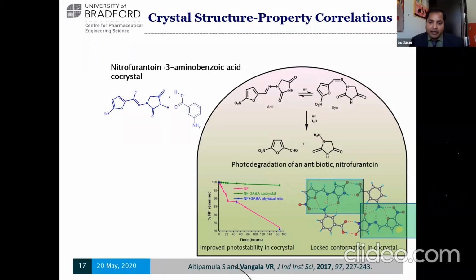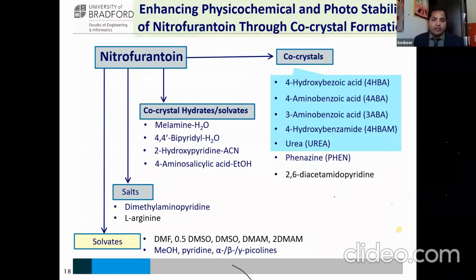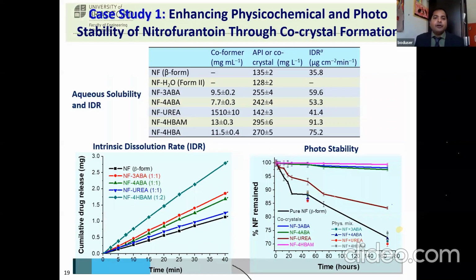Because of this folding, the locking of your coformer to the nitrofurantoin has offered complete stabilization, or it is arresting cis-trans isomerization. Accordingly, you could see photodegradation studies where a complete photostabilization has occurred. Just to continue, not to talk about details of the further nitrofurantoin co-crystals, but we have prepared very many co-crystal structures of nitrofurantoin. We have also determined the solubility and dissolution profiles.